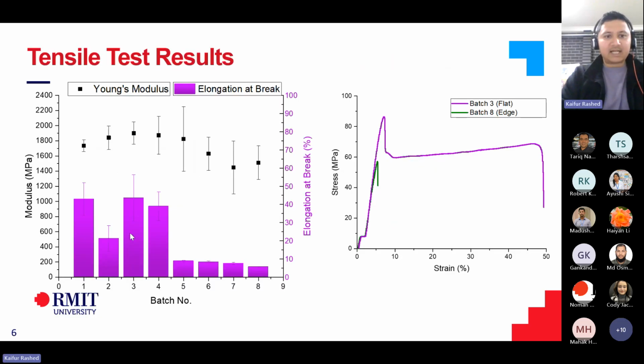And these are the results of the tensile tests. As you can see, there's a significant difference in elongation at break. The purple bars are the elongation at break. Between, say, the first 4 batches, the elongation at break was pretty high. But in comparison, in the last 4 batches, the elongation at break reduced significantly. The last 4 were printed on edge. So we can see clearly that when you're printing on edge, the material becomes more brittle, and when you're printing flat, it's much more ductile. We are speaking of a difference between 43% and about 4%, which is significant.